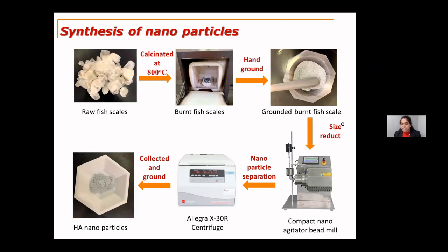After getting the burnt fish scales, they were hand ground using the mortar and pestle. Those were still macro particles, not even micro. These were sent to the compact nano agitator bead mill, which is shown here. This is a bead mill which has a filter pore size of less than 0.3 millimeters. Inside this, we use small zirconia balls of size varying from 0.3 to 1.4 millimeters. Let's say for 3 grams of burnt fish scales, I use 7 grams of zirconia balls. So we should use a 7 to 3 ratio of the zirconia balls to the material. That way it would be ground into a fine powder, or the nanoparticles.